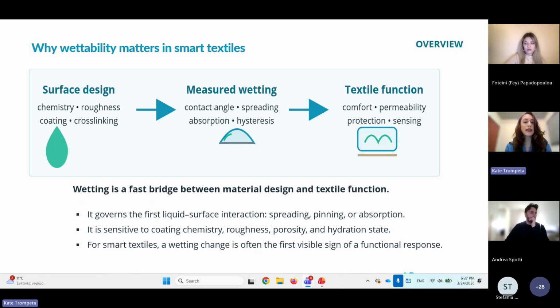For smart textiles, a wetting change is often the first visible sign of a functional response. So we need to study the surface design, its chemistry, the roughness, as mentioned before, of the fabric itself or the coating, and the cross-linking of the material on the surface of the fabric. So how is wetting measured?